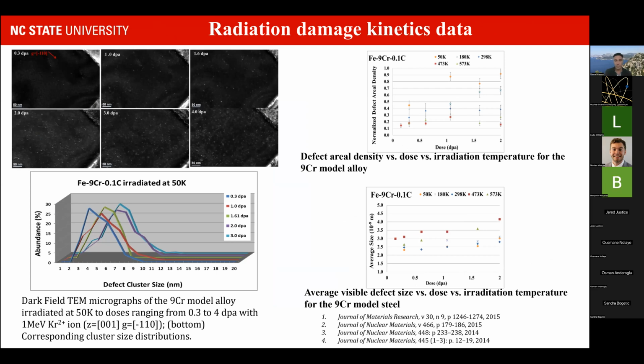As an example, I show you here a past study on pure kinetics information collection in model ferritic-martensitic steel alloys, meant to feed rate theory models. This gives you an idea of what we could do. You follow the exact same region, and as you can see, you have an increase of little white dots, and their size can increase. The beauty is that we can measure the size distribution and see how its shape evolves, and how the average defect size evolves as a function of dose and temperature, as well as their number density.